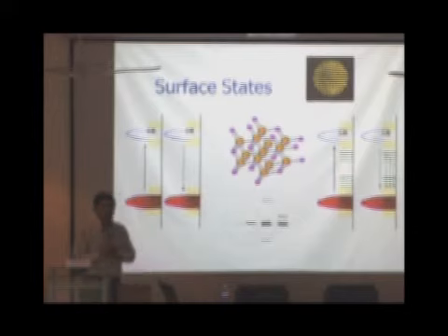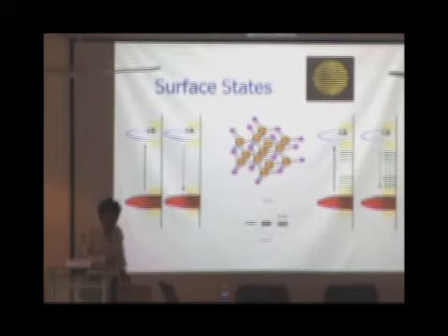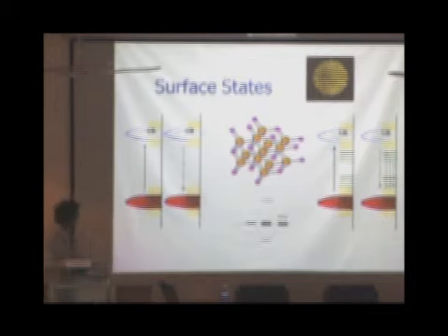Those are called dangling bonds, and dangling bonds means they are electronically placed at more or less the same level where they started with as atomic orbitals. Right? So they are not shifted anywhere because they have not bonded to anything. And if they are not shifted anywhere, they would lie between the HOMO-LUMO, or the conduction band and valence band, so within the band gap region. So these green ones are what I'm showing you as the dangling bonds.